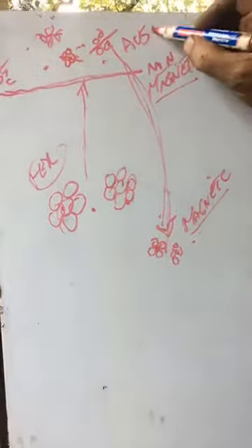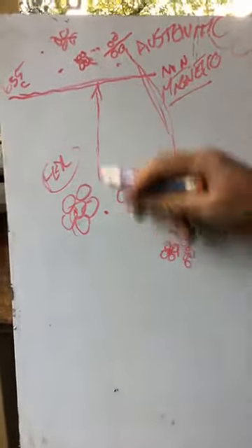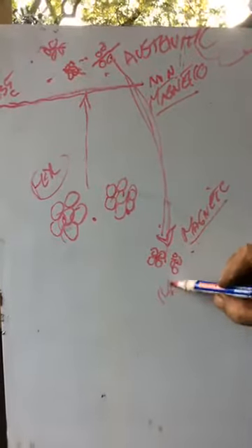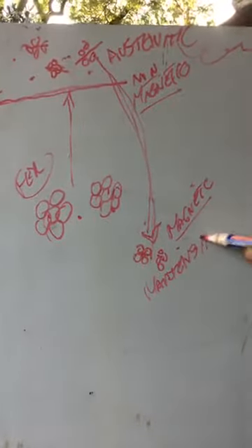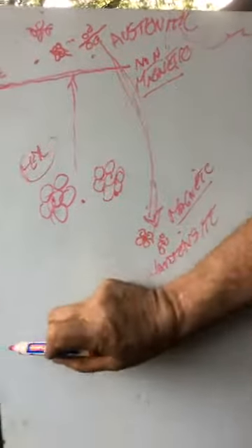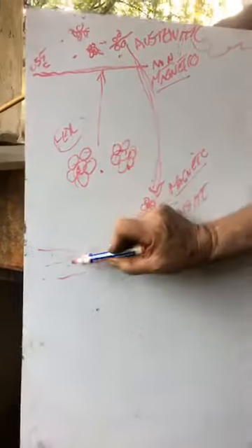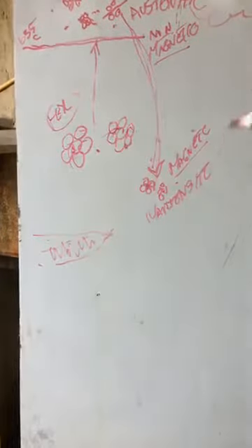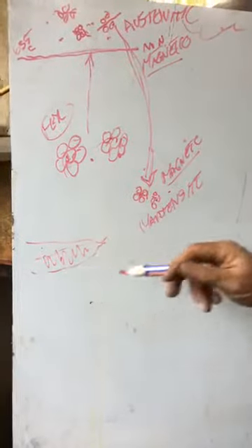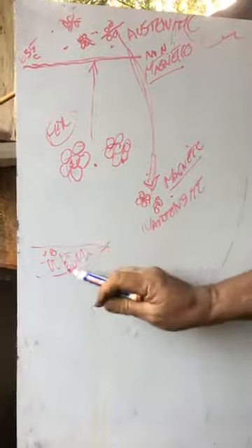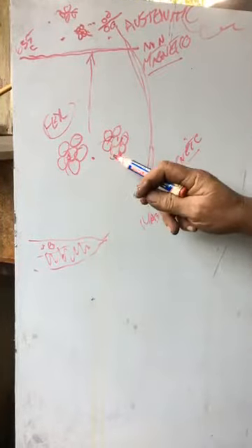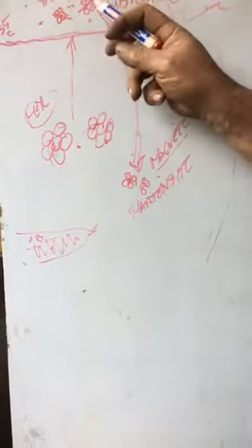So that's austenite. So steel, carbon steel is austenitic. Turns into austenite, cools down, forms martensite. And that is the magic in a carbon steel blade. And that's why you can differentially harden. So you can heat up your blade, and your edge will form martensite, and your back will retain these structures. So you'll have this very fine grained, very hard cutting edge that's serviceable, and you have a larger grain back that is soft, that acts like a shock absorber, so it can take the impact if you're chopping or cutting. So ferrite, carbon, pearlite, heats up, gets austenitic, cool it down fast, becomes martensite. And that's the whole magic of forging.